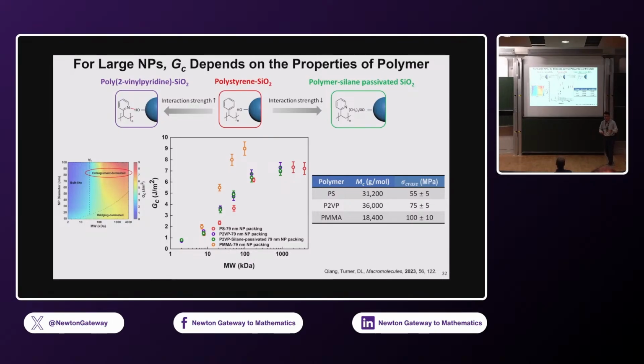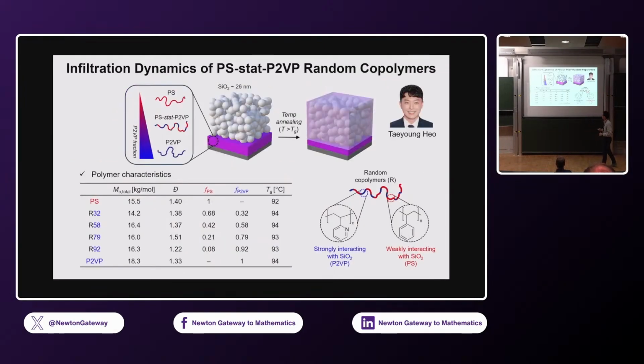Two, okay. So, I was going to skip this, but since I have 2 minutes, I'll tell you about a story that we don't fully understand. I'm going back to the infiltration dynamics. What we do here is we create a statistical copolymer of two monomers, where one monomer is not very sticky, the other one is very sticky. So it's a random copolymer. And then we measure how long it takes for the polymer to infiltrate the material.